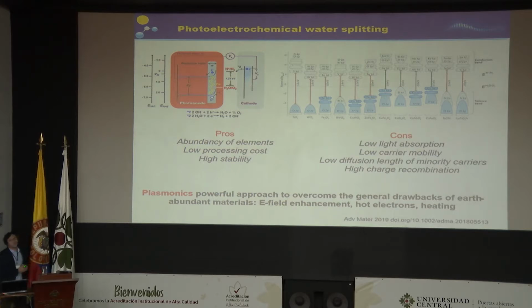When we put the semiconductor in the electrolyte, there is a formation of the so-called depletion layer. So we have band bending at the interface with the liquid. And so when we shine the light, we form electron-hole pairs which have very high energy, and that can be separated thanks to the formation of these depletion layers. Therefore, we can use these highly energetic carriers to drive chemical reactions. In this case, we are talking about water splitting, which means we have water, and we can design materials which split the water into oxygen and hydrogen. This is not so easy. The first report about water splitting was in '72, and so far there is really no technology which is commercialized about this. And this is, of course, for many reasons.